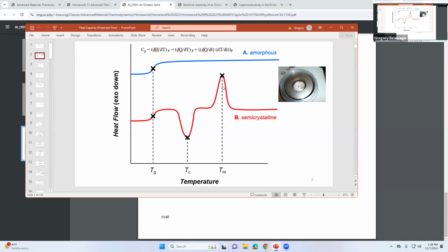There's no peak, because with polymers, depending on the thickness of the polymer, you have crystals that are like this, but some of them are really thin and some of them are thick. So the thick ones have a high melting point, and the thin ones have a low melting point. Instead of having a spike like in a metal, you get this broad thing. We have all these different crystal thicknesses that govern the temperature that melts it. The crystallization is crystallizing different thickness crystals to get a broad peak here.